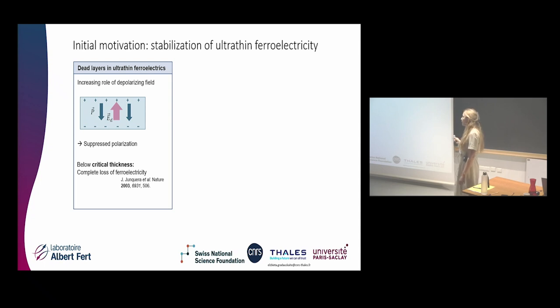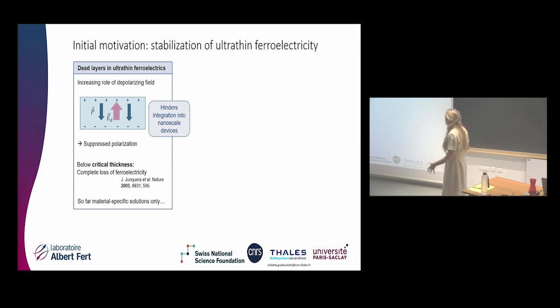It means that below this critical thickness, the material just prefers to stay paraelectric rather than ferroelectric. And once again, this is not great because now we have this wasted volume of the material that has no functionality. So far, there have been some material-specific solutions to overcome this problem, but there's really not a good way to get rid of this depolarizing field.